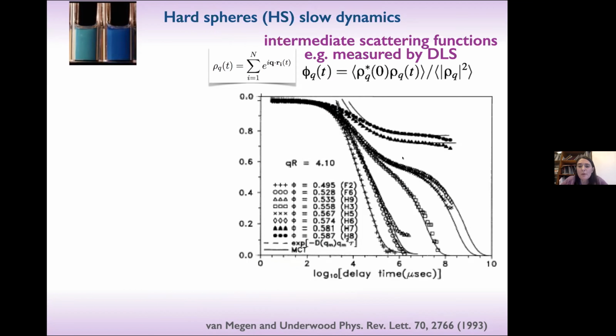Here is a picture from his very famous paper with Sylvia Underwood in 1993, where he measured the autocorrelation function of the density that is defined here, normalized by the zero time value, by dynamic light scattering. So for these glassy samples, these are the density correlation functions as a function of packing fraction at a fixed wave vector that is typically of the size of the diameter of a particle. And what happens from these measurements?